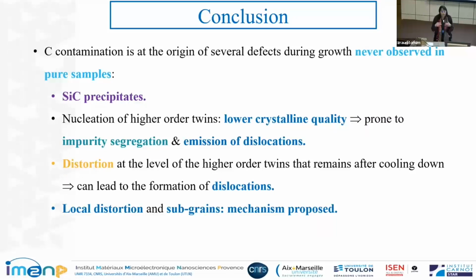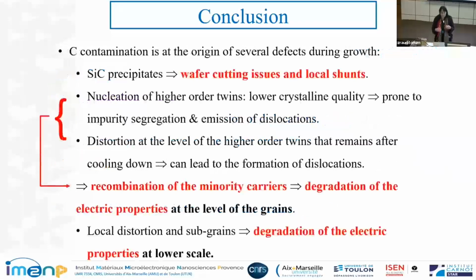So you already have defects at the level of the twin boundaries, but also local distortion at the level of these small features I showed to you and subgrains. And all this will have an impact on the properties of the material when you want to use it to fabricate solar cells. The precipitates give some difficulties for wafer cutting and also induce dislocations. These higher order twins will be sites of recombination of minority carriers and degradation of the electrical properties at the level of the grains, and same thing for the smaller scale defects.